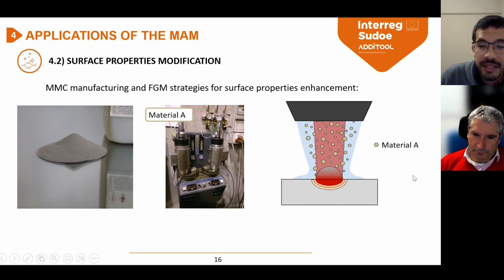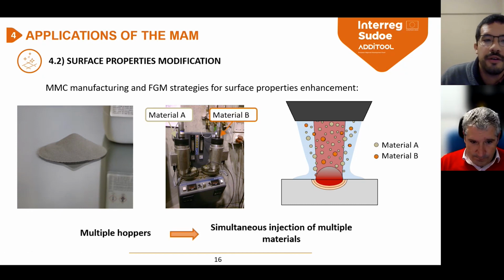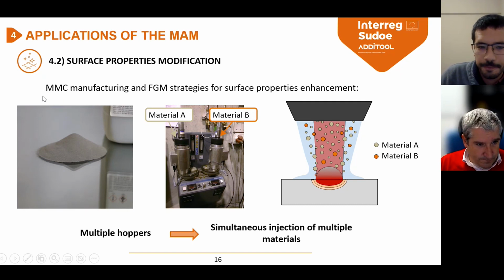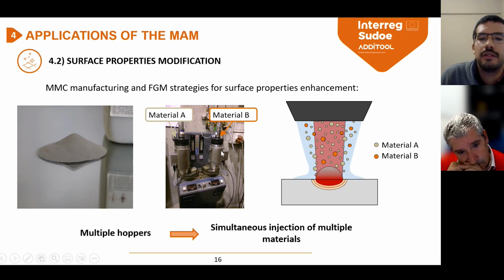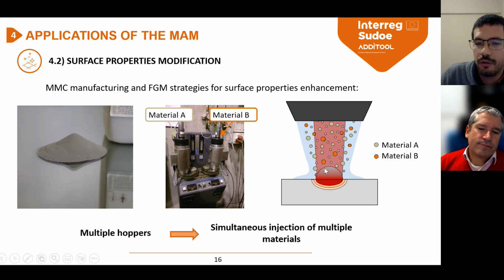However, in metal additive manufacturing, we can combine different materials in order to obtain what is called a metal matrix composite. In this case, we add 2 materials simultaneously, and the clad consists of a combination of both materials. Moreover, we can control the feed rate of both of them and the ratio we are feeding, and we can build what is called a functionally graded material. We can control the chemical composition of the clad, and we can vary that chemical composition in every clad or every layer.